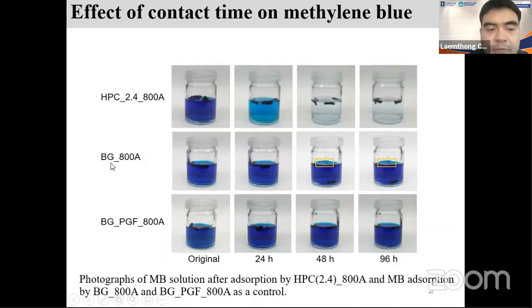If you use only bagasse and you burn it, you get this kind of stuff, and it is also no longer floating on the water surface after 96 hours, so around 3 days. But look at the top here: you don't need to do anything. You just put it on the surface of the water and let it sit. You might stir it a little bit, but after 3 days they still float on the water surface. So it's quite easy to remove from the system, just by using your hand to pick it up, right?